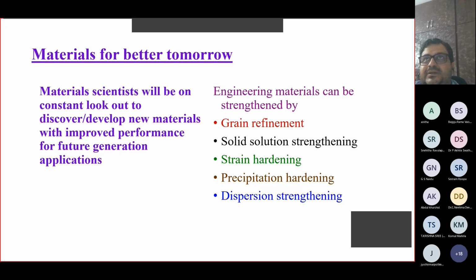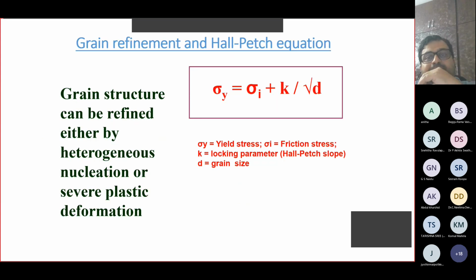For example, in aircraft materials, the majority of aluminum-based alloys are precipitation strengthened materials. And the other part is dispersion strengthening, and these are a totally new set of materials where the dispersions, you can call them second phases or fillers or any other name, are not coherent to the matrix. They're totally incoherent, and this is good for high temperature applications. As I mentioned before, this is the Hall-Petch equation. So this grain refinement can be obtained by heterogeneous nucleation traditionally, but it sets a limit. Beyond say 4 or 5 microns, heterogeneous nucleation will not be of any help in making fine-grained materials, in other words, nanomaterials.